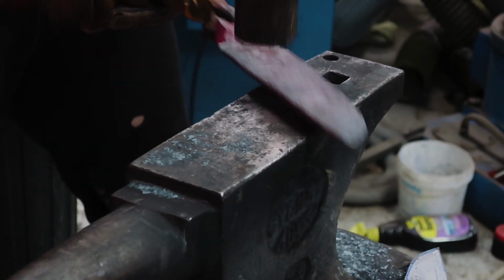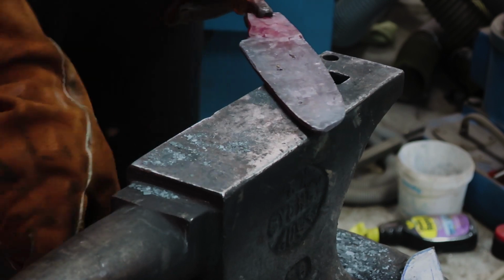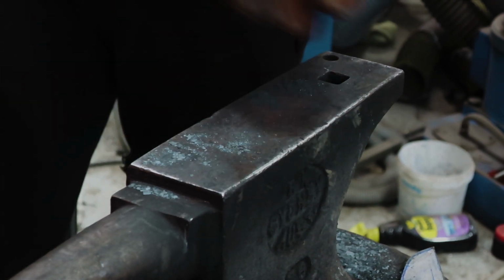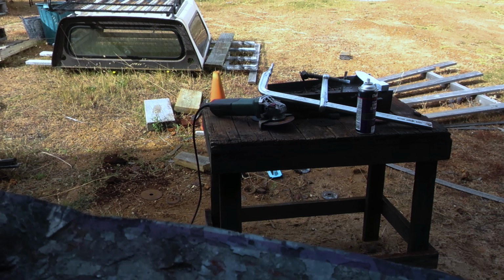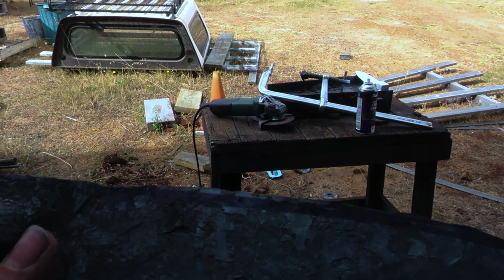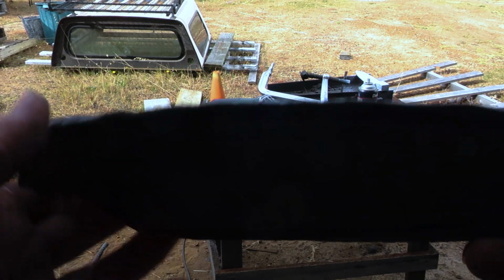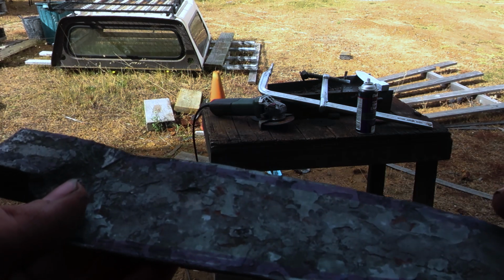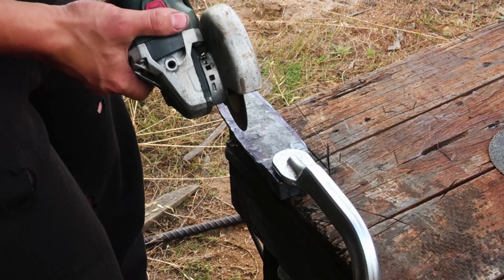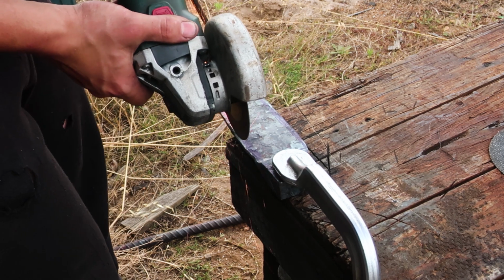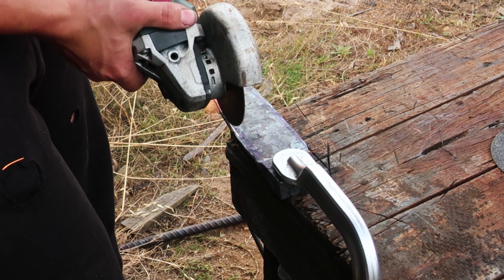I'm not good at forging. I mean, usually I do mosaic Damascus, so I rarely forge the shape to avoid distorting the pattern. But with sanmai it actually helps, because you don't want to grind those side layers off, and it also creates more activity at the transition from the core outwards. Now I have tungsten all up in this chisel, and this is from the chainsaw chain, which obviously was not planned. I'm not sure how I'm going to combat it, but at the moment I'm thinking of brazing it, but we'll see.